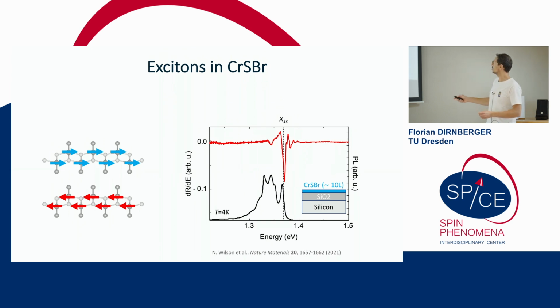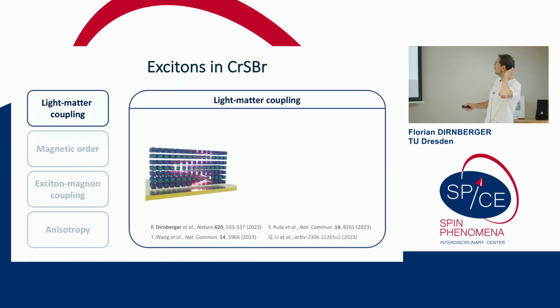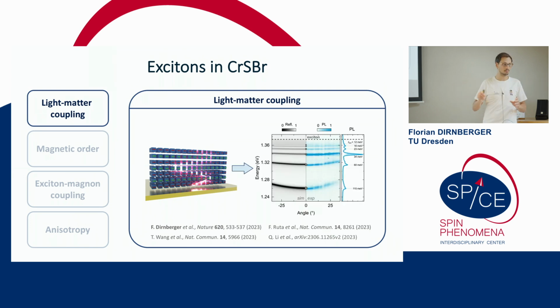Okay, so just very briefly, one thing that I particularly investigated before I started working on the exciton transport in chromium sulfide bromide is the coupling of the excitons to light. As I said, their oscillator strength is really large, which means these excitons like to interact with light. And one thing that we figured out quite some time ago is that the excitons in bulk crystals couple even more strongly with the light that is confined by these crystals, and then you get all of these polaritonic properties. If you take a crystal that has a thickness of 100 nanometers or so, the excitons strictly within the light cone don't exist. So you should really think of this in the picture of exciton-photon coupling in polariton language.